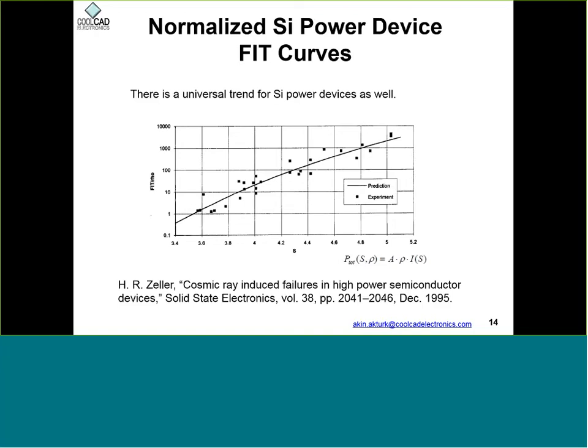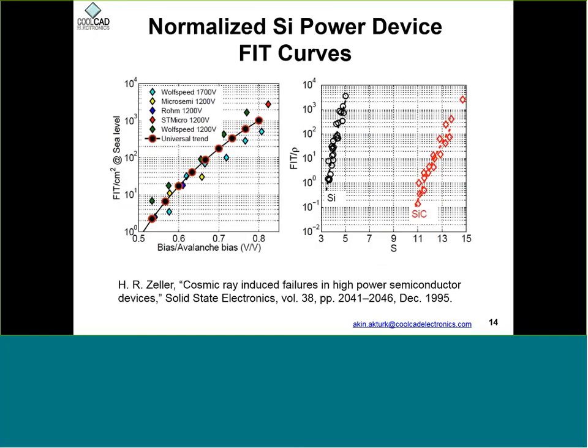And this was done back in the 90s by Zeller, who I think he used to be at ABB. He may still be there. And they did these silicon studies, and they get these curves to get a universal trend. So there's a similar trend in silicon carbide as well. So what we're doing right now is we also try to characterize it for silicon carbide so it can be used in calculations.